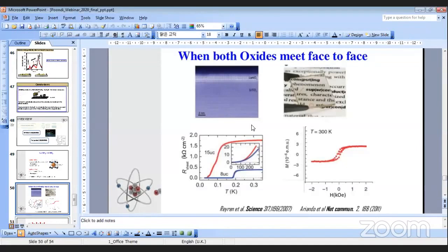So you will have 0 charges on the strontium titanate, but when you go to the interface, there is a sudden jump for lanthanum aluminate. This will have plus 1 and minus 1 layers. So there is a charge catastrophe.